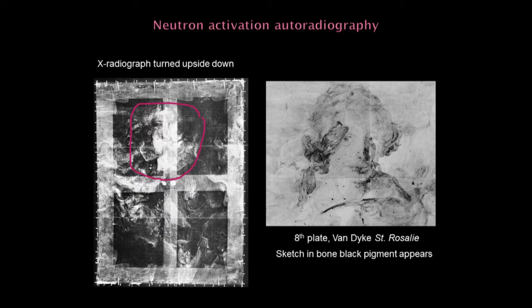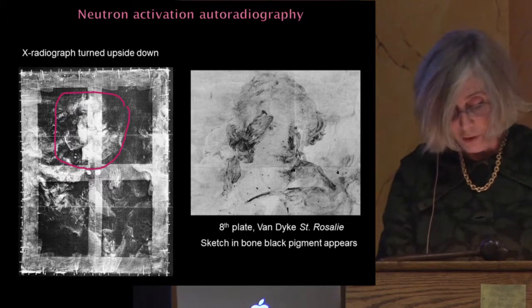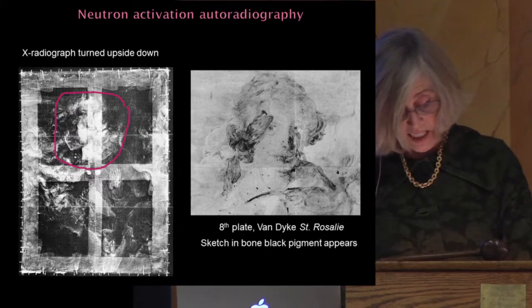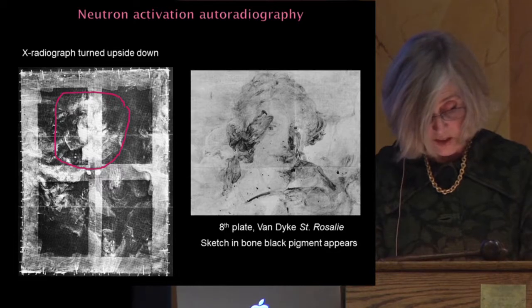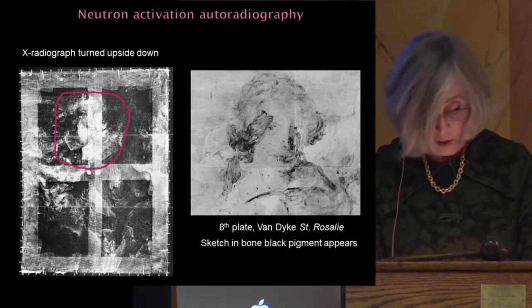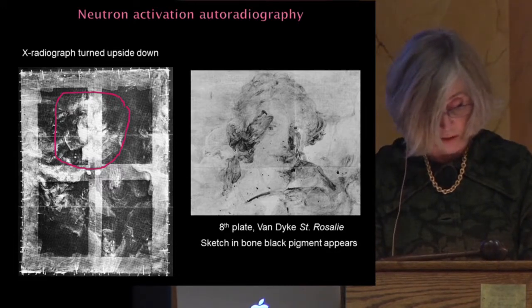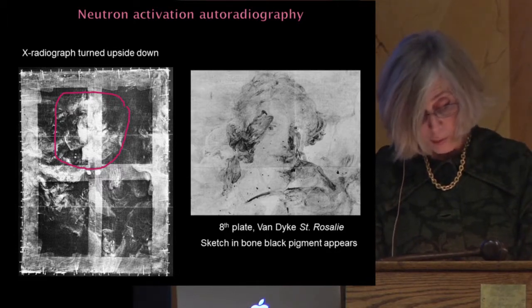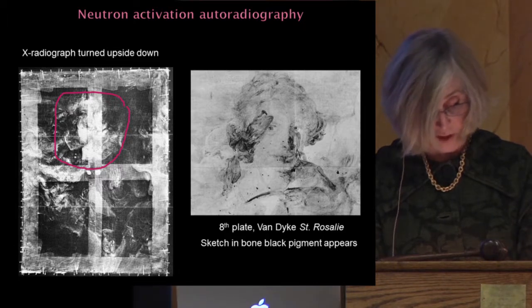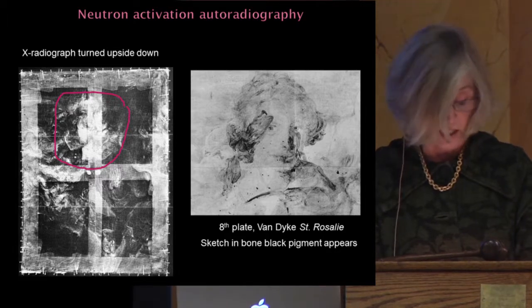A typical image might reveal a complete underpainting in umber paint, while a later film might show changes made primarily in copper blue. The downside of neutron activation autoradiography is that it can take a long time, depending on the pigments, involving minutes, days, or even weeks after the initial exposure, and it also involves making the painting radioactive, although the institutions who use the technique do not feel that this damaged the painting in any way. Because of the neutron beam, it also requires transport of the painting to a reactor facility and its extended stay there. Obviously, this is not a practical analytical technique for most museums.